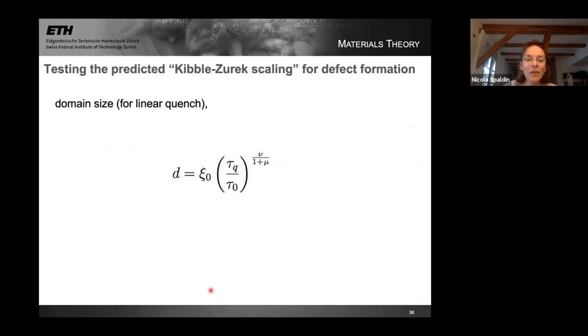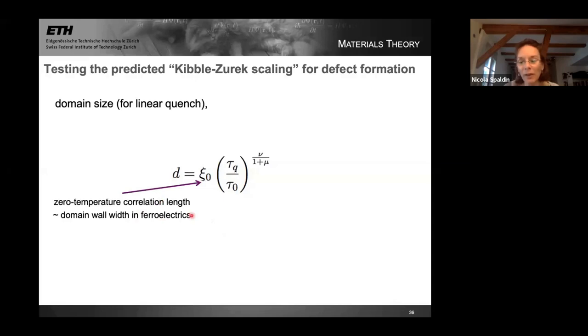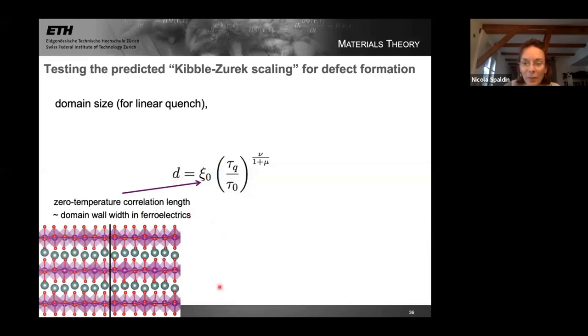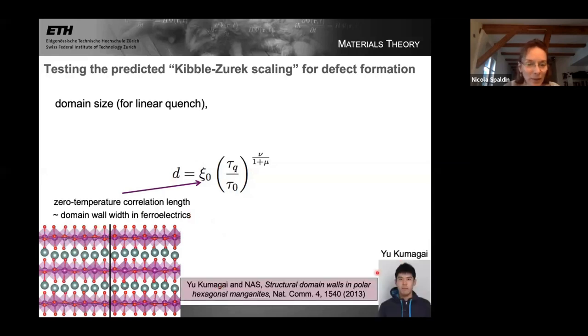So let's actually quantify this. The predicted Kibble-Zurek scaling for formation of topological defects tells us the size of the domains we should form as a function of how quickly we go through the phase transition. So let me tell you what all of these parameters are. This xi zero is the zero temperature correlation length, which is approximated in a ferroelectric by the width of the domain wall. This we calculated. This was calculated by Yu Komagai, who's now an assistant professor at University of Tokyo.